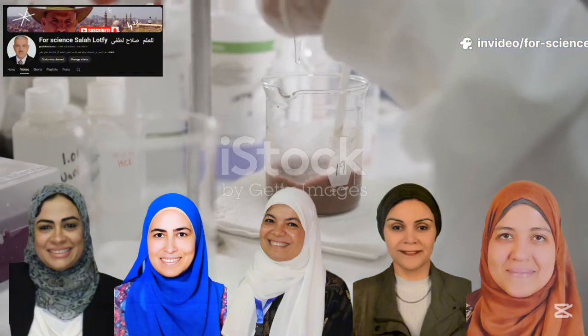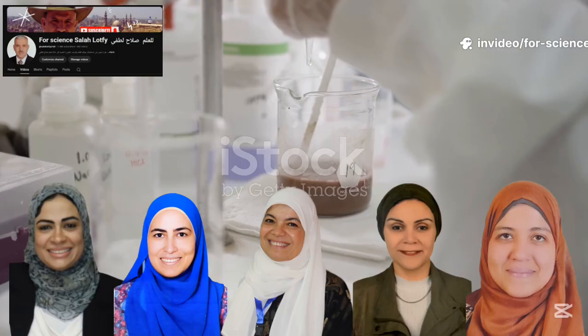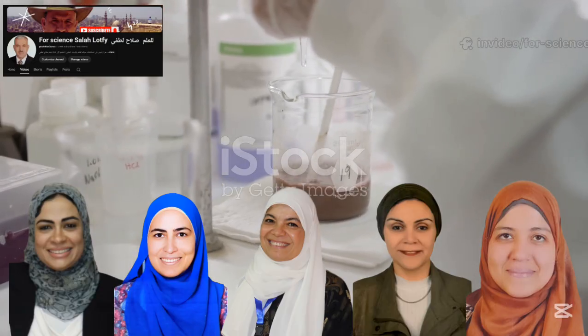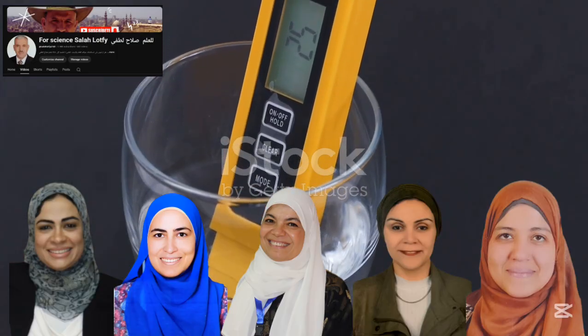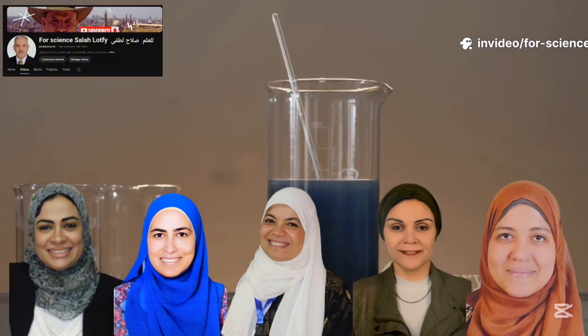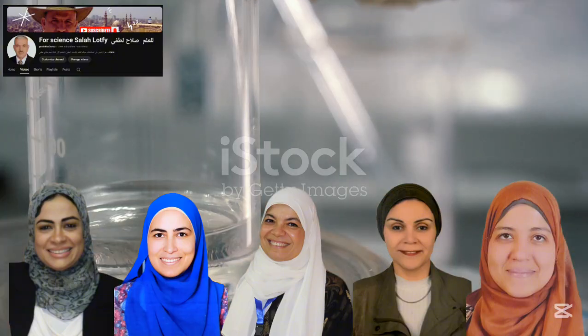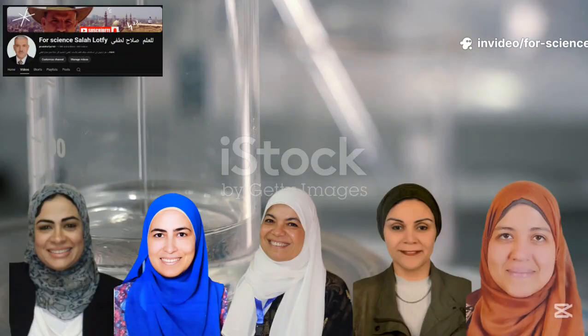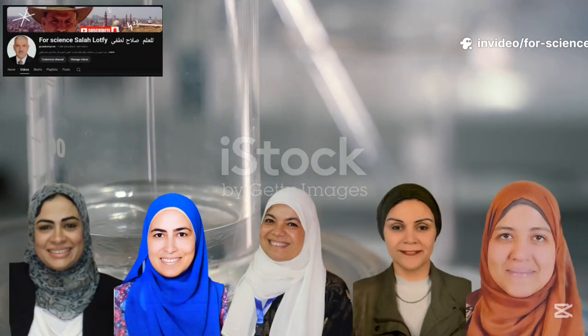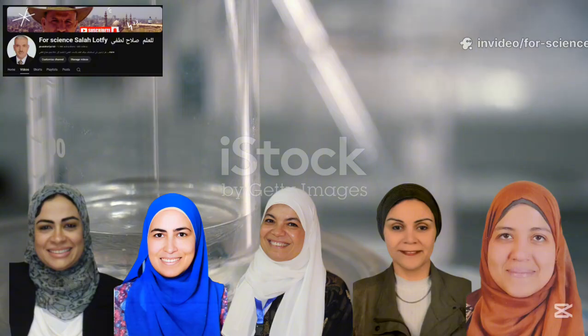Next, a sodium hydroxide solution was introduced as the precipitating agent. It was added drop-wise into the precursor solution, a critical step for ensuring uniform nucleation and growth, which leads to a consistent nanoparticle size. Throughout this addition, the reaction was maintained at a constant temperature of 60 degrees Celsius and a pH of 8.5. The temperature governs the reaction rate, while the specific pH promotes the formation of zinc hydroxide and the incorporation of silver. As the base was added, a milky white precipitate of silver-doped zinc hydroxide instantly formed.